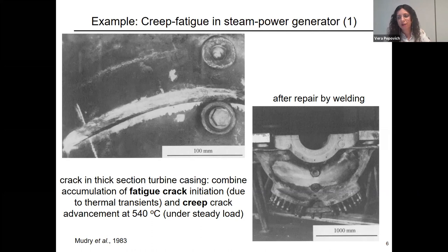So the creep aspect we are going to look into, but the crack actually advanced subcritically due to creep, because this power generator operated under high temperature for a prolonged time, 17 years. And it's experiencing steady load, under steady load a creep deformation. So the crack further propagated and resulted in a failure in this particular case. So keep in mind that in a lot of high temperature applications, it's not just one failure mechanism, but a combination. In this particular case, it's fatigue and creep. But quite often we are also looking into oxidation, so high temperature oxidation on top of that.